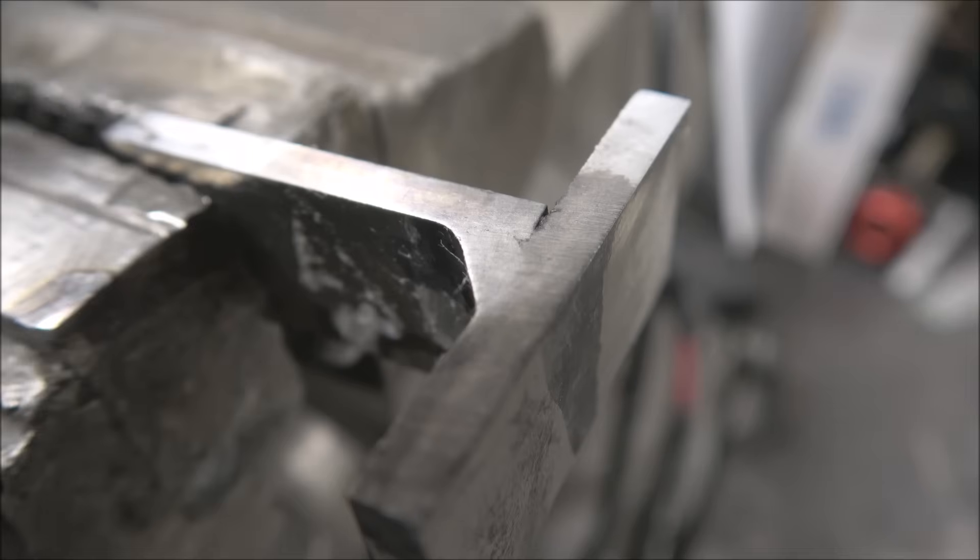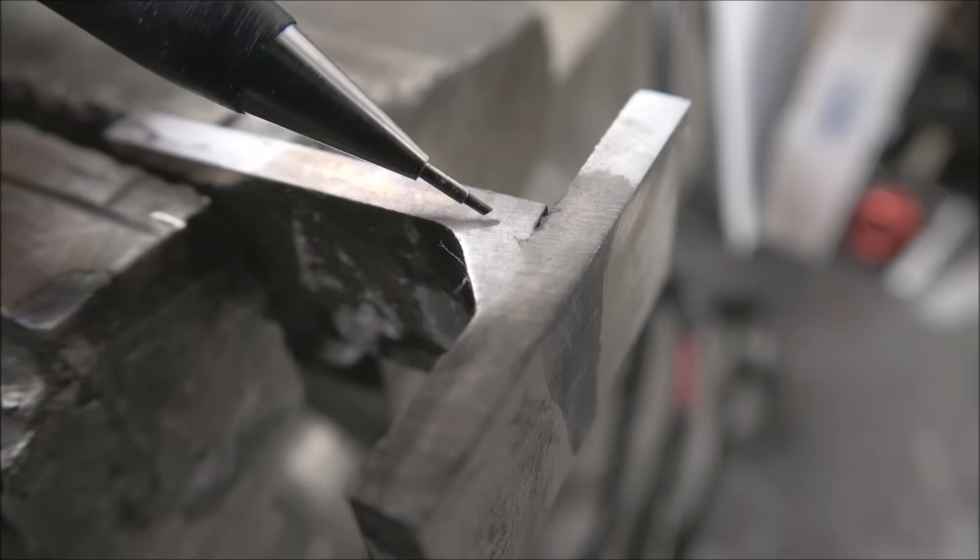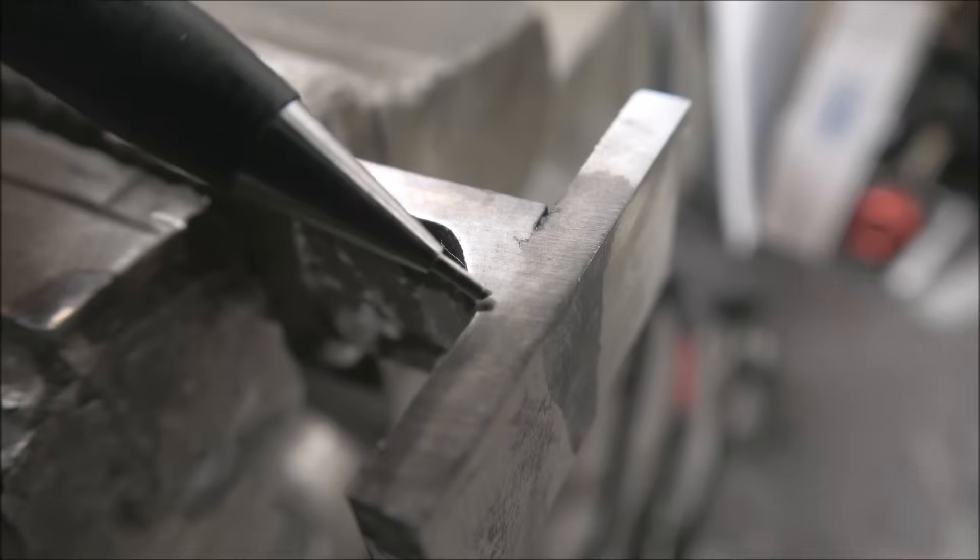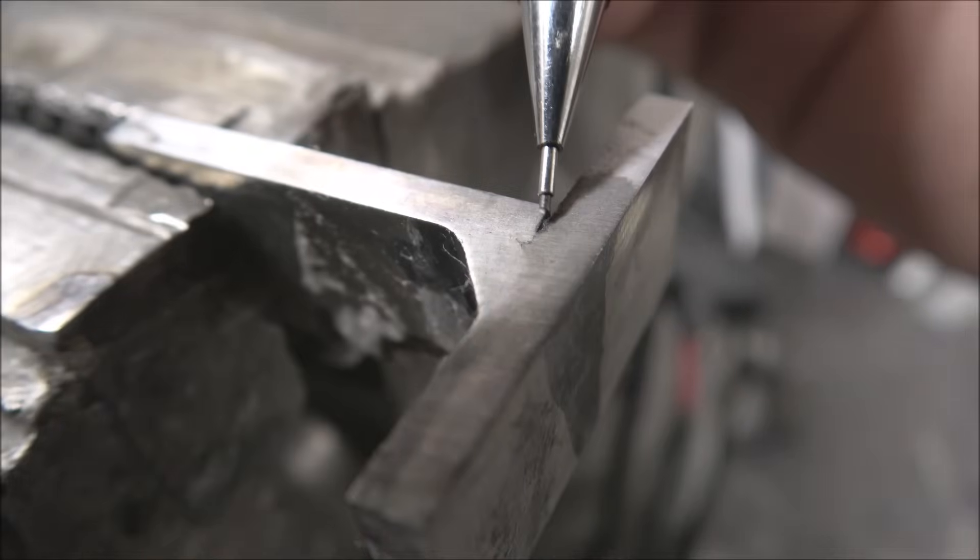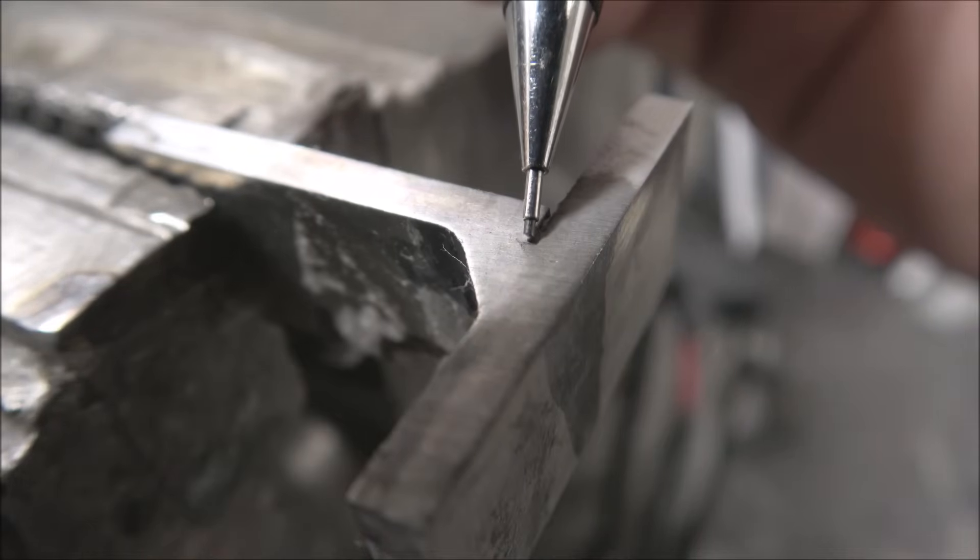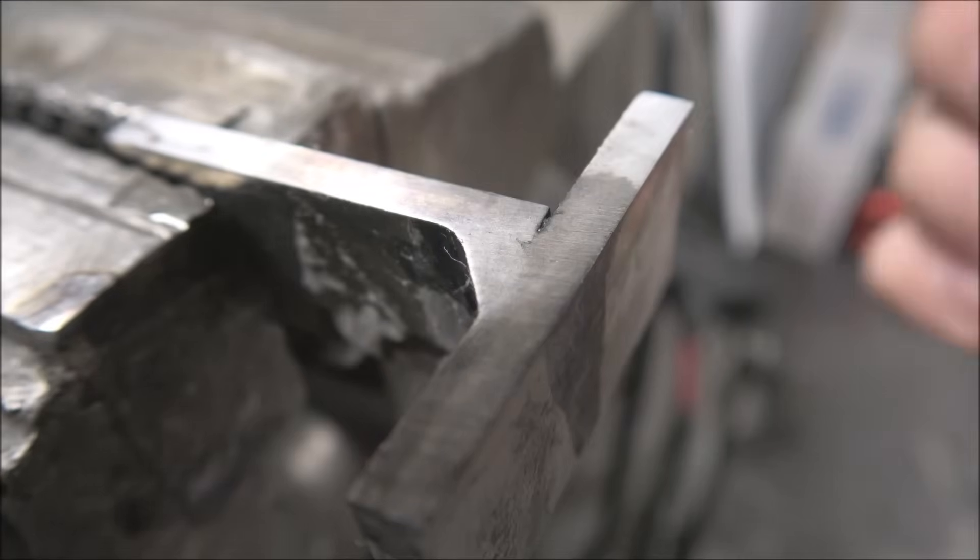Okay, that one feels pretty strong. Let's put it in the vise. And for all you cutting edge nerds out there, you can see where it's liquefying in. Looks like there's a little crack splitting out right here at the base where the filler rod didn't fuse in. I'll do a couple more welds and burn in deeper after this.